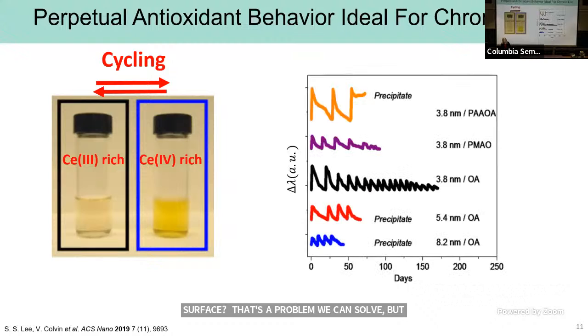Okay, let's see, good. So one of the ways that we measure the success of these systems is we actually just treat them and study their antioxidant recycling capacities. And so some of these materials are very, very good at it, and they don't last forever, but they certainly can absorb huge quantities of reactive oxygen species multiple times. And so they go back and forth, and they can be challenged over the span of days or even months.